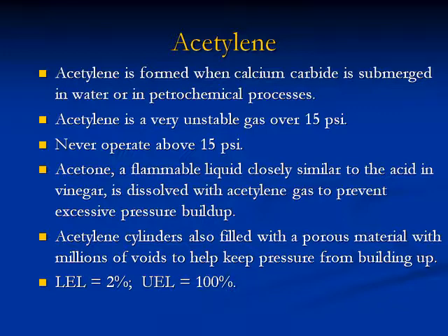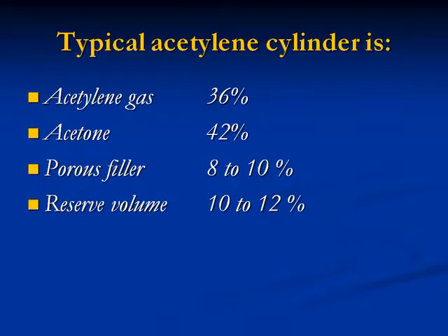Acetylene cylinders are also filled with a porous material with millions of voids to help keep pressure from building up. LEL equals 2%, UEL equals 100%. A typical acetylene cylinder is acetylene gas 36%, acetone 42%, porous fillers 8 to 10%, reserve volume 10 to 12%.